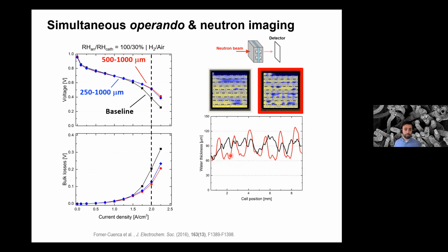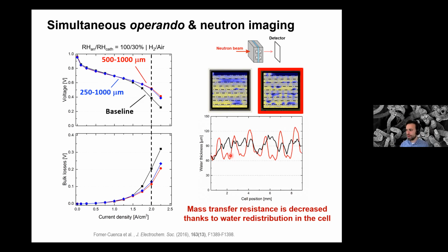And you can see that the water preferentially locates on these hydrophilic patterns that we created before. So the interesting thing here that we learn is that the total amount of water is about the same. So it's not that by making hydrophilic patterns, you get less water in your porous media. You get about the same total amount of water, but what changes is actually the distribution of this water. And if you have 30% of the area fully saturated, but 70% nearly empty, that would already give you a fundamental advantage in terms of mass transport.